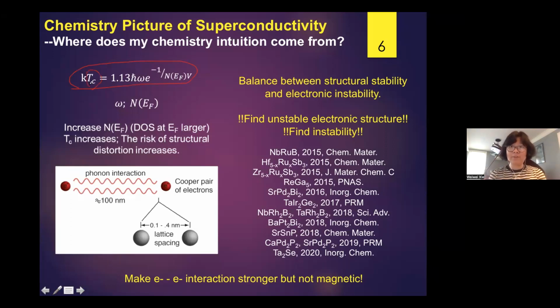And for the conventional superconductor, if we want a higher TC, we have two ways. The first way is we make the electron-phonon coupling, the vibration, higher. And the other way is we make the density of states at the Fermi level higher. So to make the electron-phonon coupling higher, one way is to combine light elements with heavy elements. Then the vibration will be stronger.